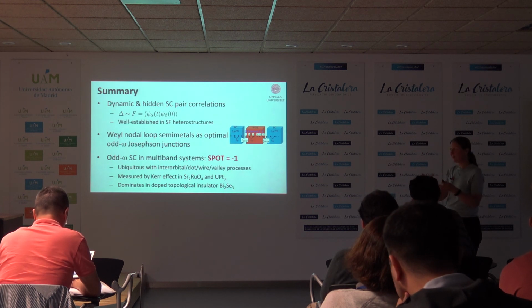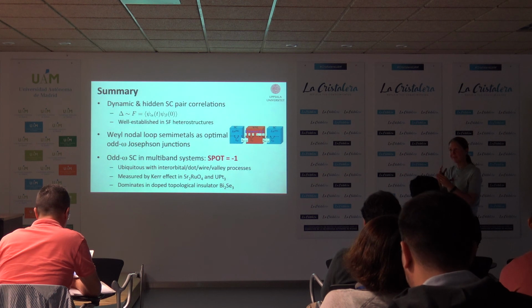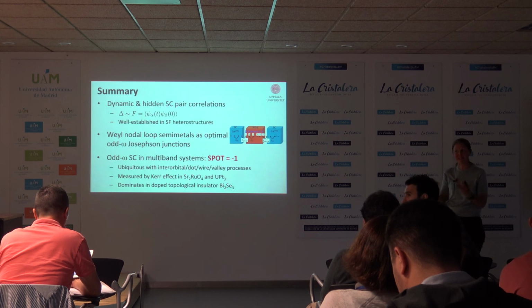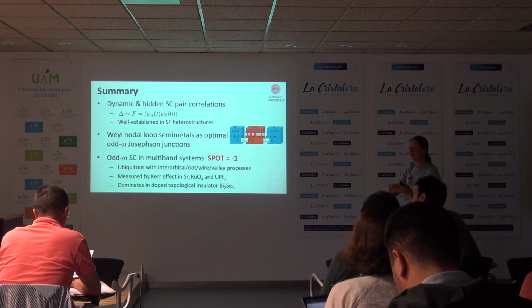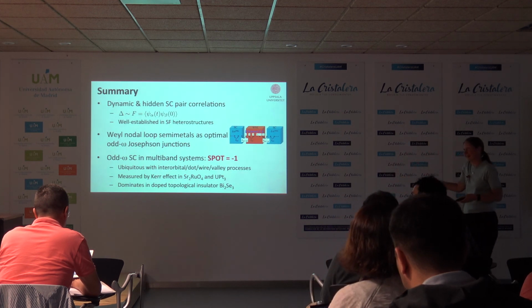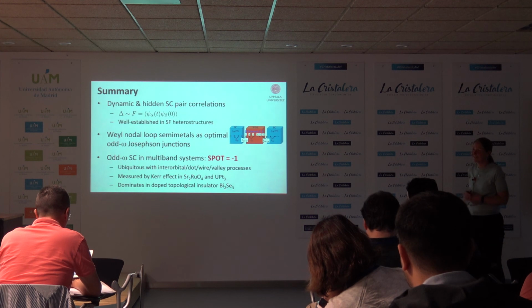On the other hand, if you complicate the normal state enough, you can still get it. For example, these topological systems are a good example where you always have two orbitals. You can't get two bands without having two orbitals, and they're intrinsically mixed. And you also mix the spin parts, because it's often k dot sigma or something. So my answer is yes, I agree with you, but I think there are counterexamples where it seems to actually work. Maybe Tc will never be very high in this material, so, as I said in the beginning, this is probably not high-Tc stuff, but low Tcs seem to happen.